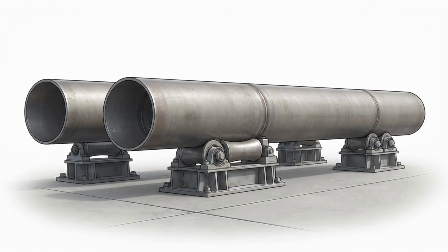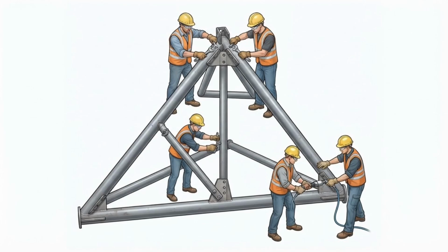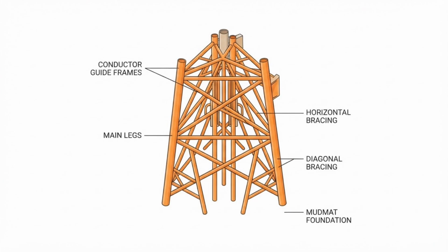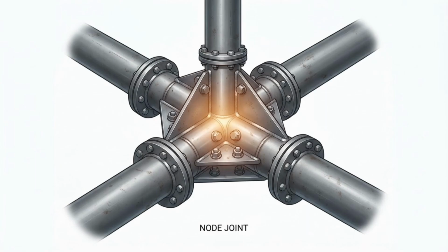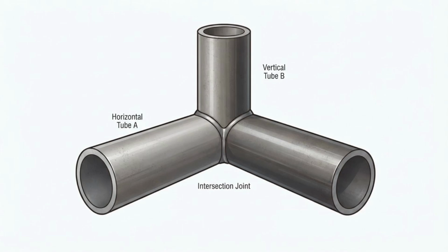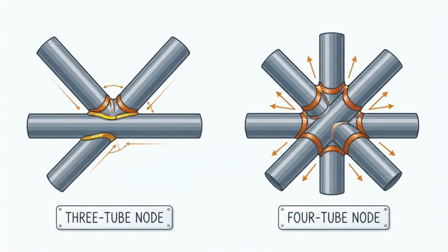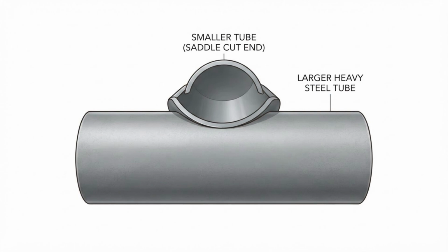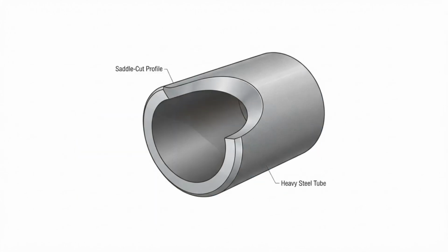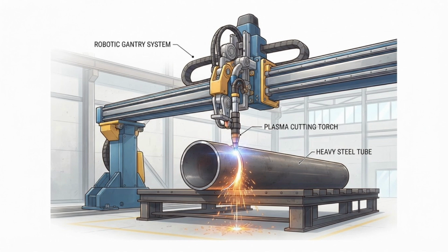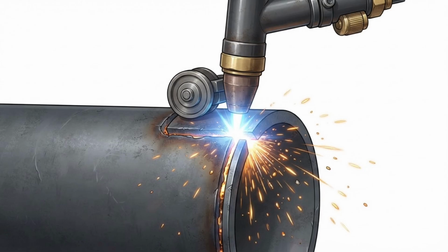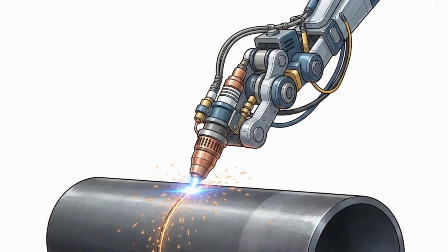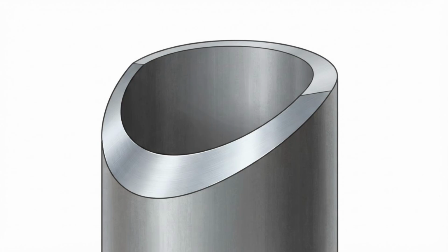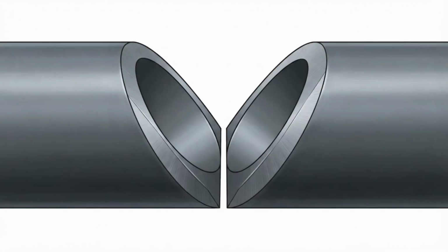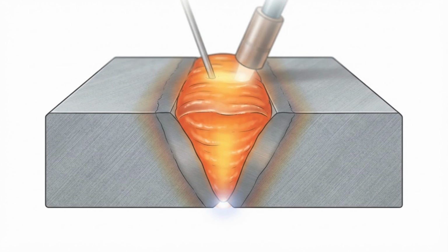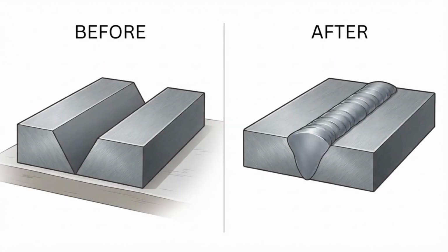These individual steel tubes must then be joined together to form the massive truss structure of the rig's hull or jacket. The most critical points in this framework are the nodes, the complex intersections where 3 or 4 gigantic tubes meet at varying angles. Cutting a smaller tube to fit perfectly flush against the curved surface of a larger tube requires a specialized saddle cut. Giant 5-axis computer-controlled plasma cutters slice through the thick steel, continuously adjusting the angle of the plasma torch to create a precisely beveled edge. This bevel ensures that when the welders fill the joint, the molten metal penetrates all the way through the thickness of the steel, creating a full penetration weld.